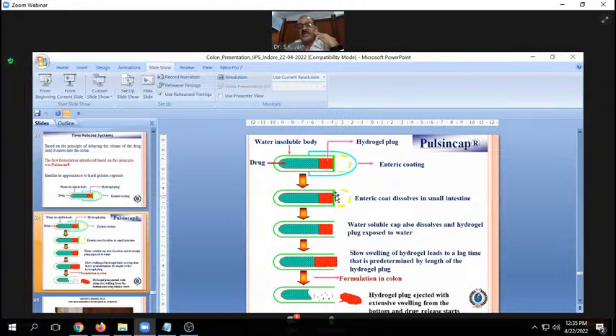When it reaches the ileocecal region, the enteric coating is dissolved, the cap is also dissolved, and this hydrogel will be exposed to the water in the ileocecal region, and will start expanding due to the swelling. So there is a slow swelling of the hydrogel that leads to a lag time that is predetermined by the length of the hydrogel. So that lag time we can control by changing the length of this hydrogel.